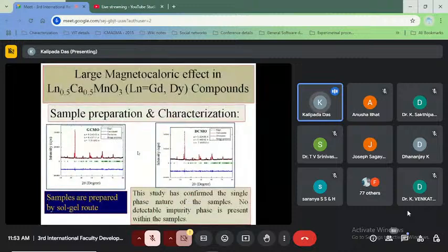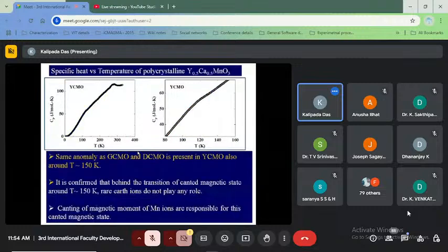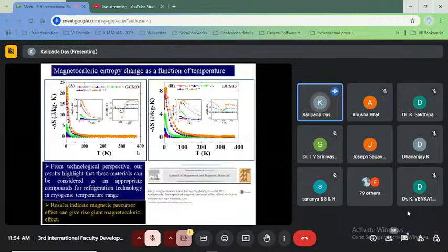Another part is the magnetocaloric effect. We already said that for practical utilization, the sample needs a large magnetocaloric effect at room temperature for room temperature application, or at liquid hydrogen temperature for cryogenic application. So we have selected some materials for large magnetocaloric effect, one of the series being lanthanide calcium manganite, LnCaMnO3, where the Ln site is gadolinium or dysprosium. In both cases, we see that the magnetocaloric response is enhanced manifold, and a large magnetocaloric effect is found in the gadolinium calcium or dysprosium calcium sample.